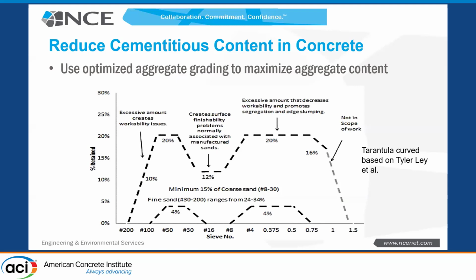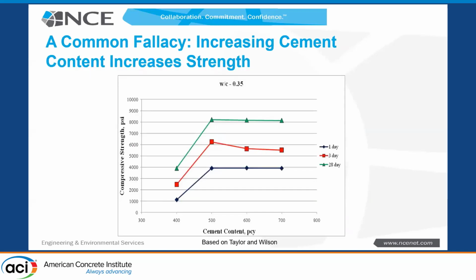But the bottom line here is there are tools available to take your aggregates. If you're working with concrete, you should not be thinking of it as coarse and fine aggregate. You should be thinking of the blend of the aggregates and filling space with as much aggregate as we can, getting the workability that we need, and yet minimizing the need for paste. When we approach it this way, we can reduce our paste quite a bit and fight a common fallacy. And the fallacy is that somehow more cement, more cementitious materials equals more strength.